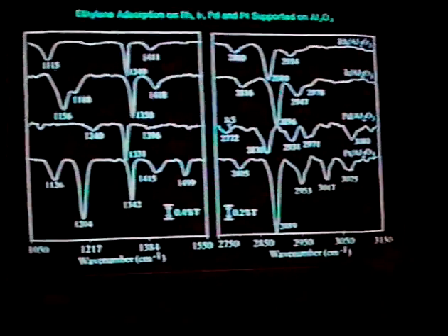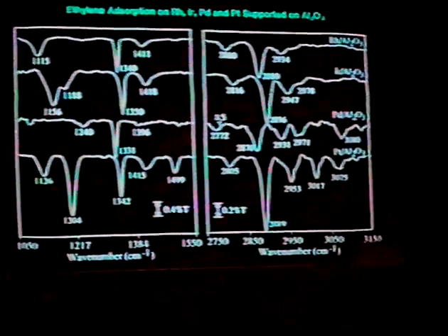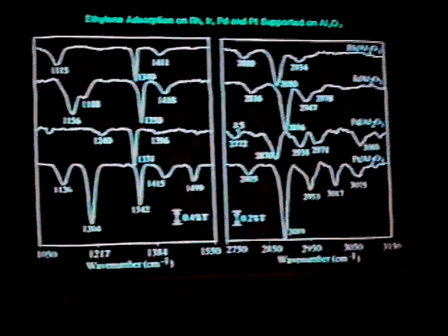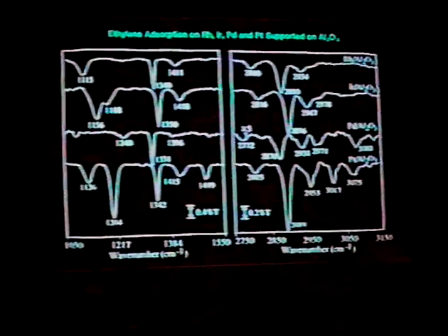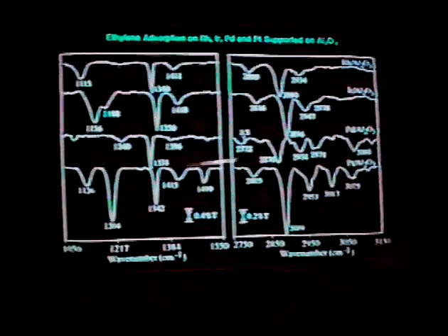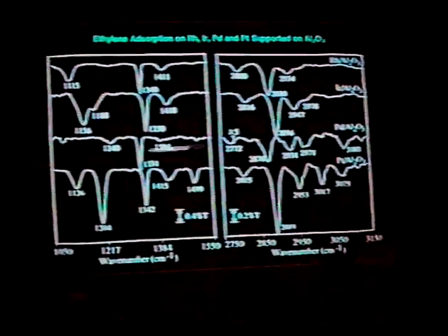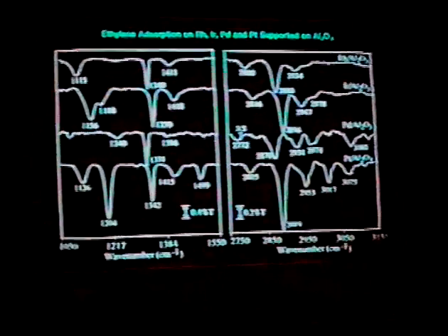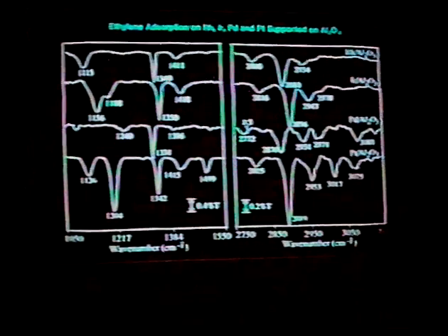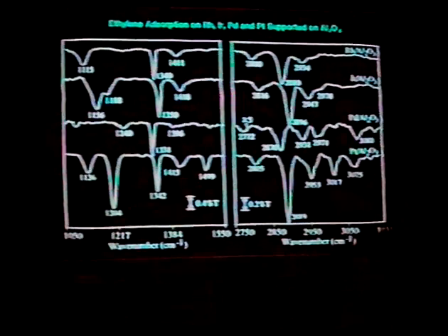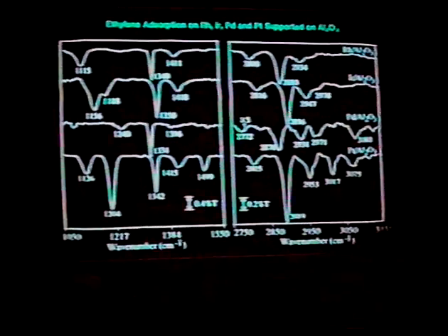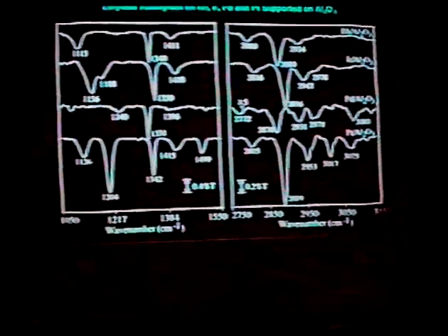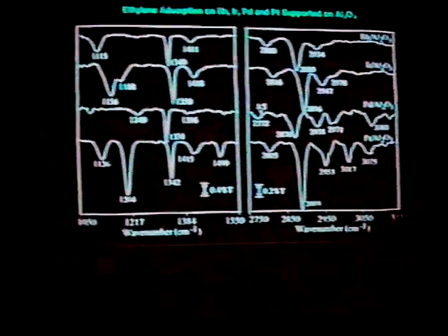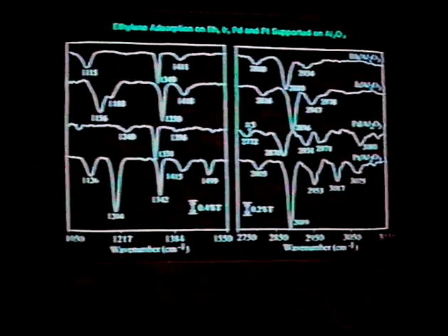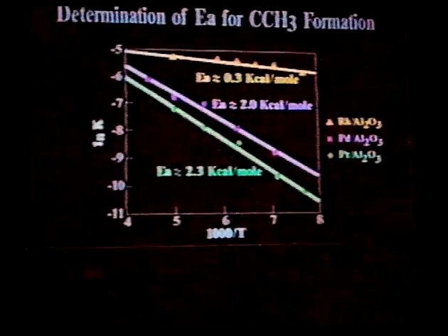I'd also like to point out that this deviates again from what's in the literature, and the reason it deviates is because all these catalysts were pretreated at a higher temperature. So the effect of pretreatment temperature on the stability of the pi-bonded species had not been previously observed on palladium at all. It does appear to be not simply a consequence of the fact that we were using platinum. And as was pointed out in today's plenary lecture, there were pi-bonded species left on the platinum silica catalyst, and I would be very curious to find out if it's a support effect. So it opens an opportunity for looking at these metals on a variety of different supports. As in the case of the